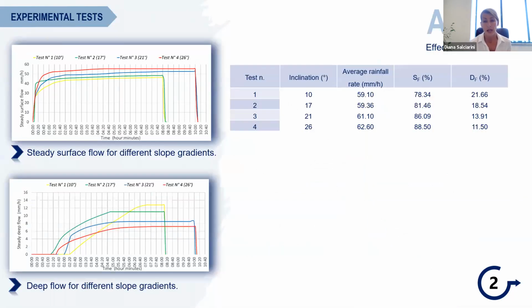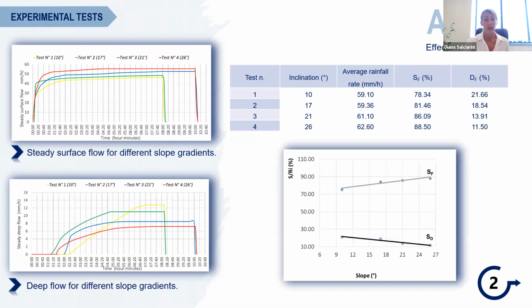As for the group A of tests, we tried to quantify the effect of steepness on the surface flow, and thus the experiments have been carried out considering different inclinations, from 10 degrees up to 26 degrees, under the action of a heavy rainfall. As you can see from the table, the average rainfall rate was about 60 millimeters per hour. Surface and deep flows were monitored, and the graphs show the evolution of the surface and deep flow in time for the 4 tests performed at different inclinations.